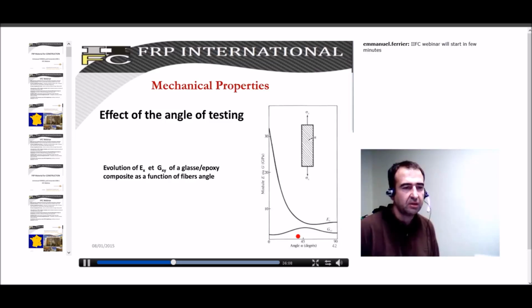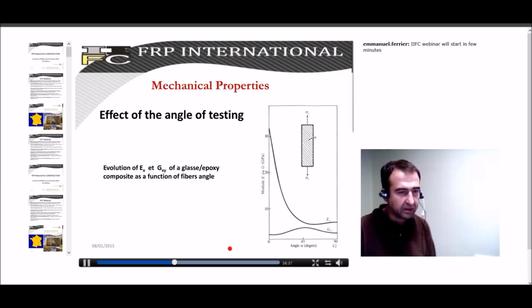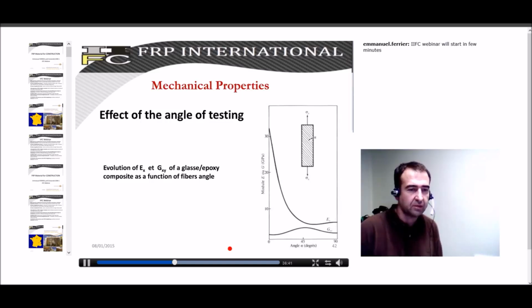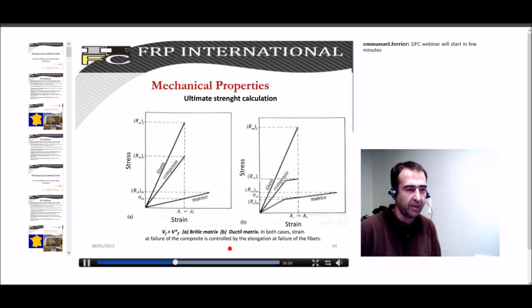Another thing that is well known in this field is that when we use these unidirectional FRP materials and they are tested in another direction, we rapidly lose the mechanical strength for a very, very low angle. It means that the decrease in Young modulus or strength is very high, and this material should be only used in its own axial direction and not in another, which can be a problem mainly for a full FRP system. But in case of strengthening, generally the fibers are bound in the direction where the force is applied.